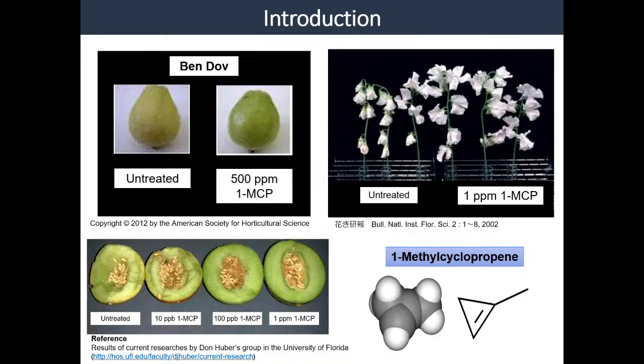So when we use 1-MCP at 500 ppm, this is the University of Florida's data on watermelon: untreated, 10 ppb, 100 ppb, 1 ppm. And then also, when we use the flower storage under some conditions at 1 ppm, 1-MCP treatment case, we can see the freshness improvement.